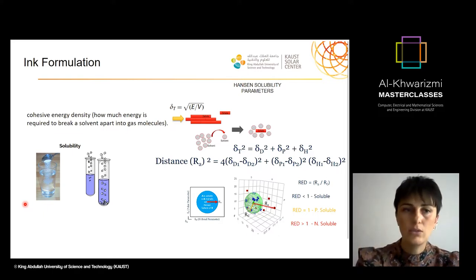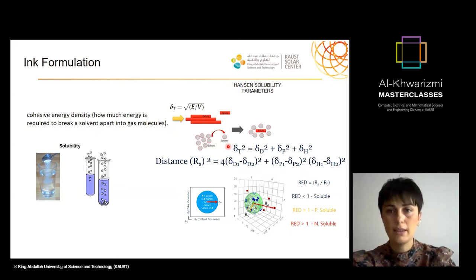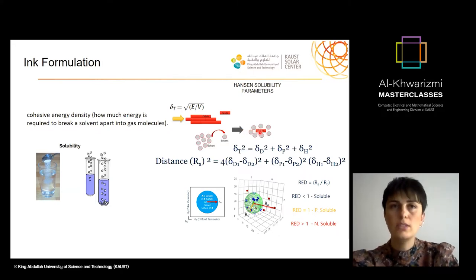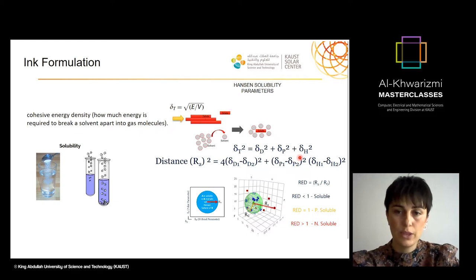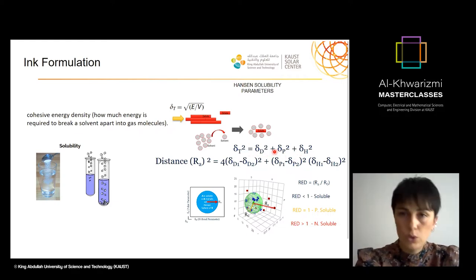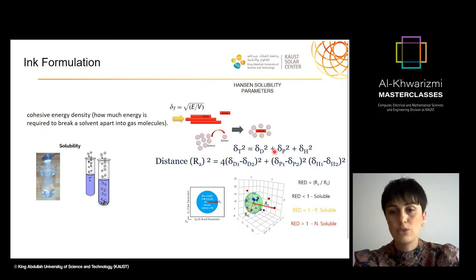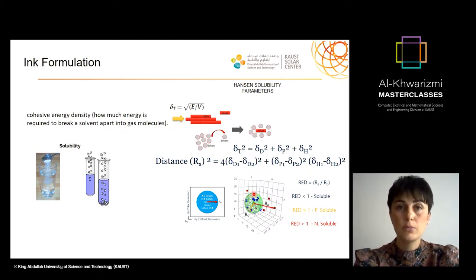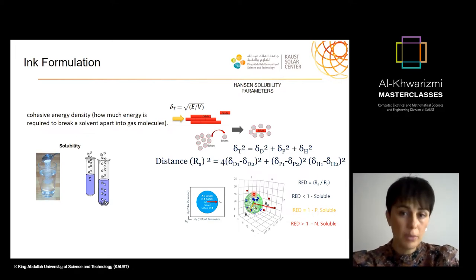And in order to do that, you're looking at cohesive energy density and then the Hildebrand parameters, which look at the solute and solvent interactions. So the Hansen solubility parameter considers three different specifications of a solute or a solvent, which are the polar and dispersive forces that are effective and the hydrogen bonding. And by considering this for the solute and the solvent, you can create a solubility sphere, as you see here in green, that tells you if your material will be soluble in that specific solvent or not, or a combination of solvents.